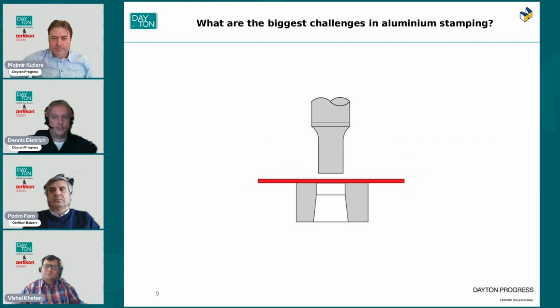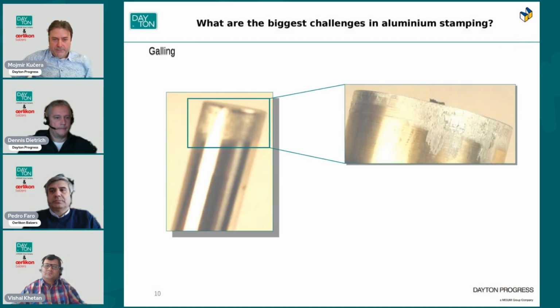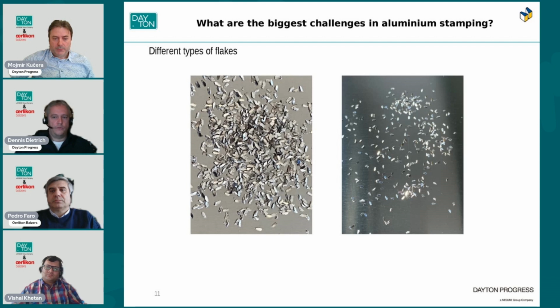Adhesive wear is caused by friction between the surfaces of the punch and the sheet metal blank. When punching non-ferrous materials such as aluminium, aluminium alloy, copper, or brass, material sticks on the punch. This leads to the formation of a build-up edge and later to flakes when the punch dives into the die. Here we now see two pictures of punches with galling. Punches with galling cause fractured or broken punches, stripping problems, poor quality holes, fast tool wear, or flake generation. In these two photos, we see flakes taken from a tool in which aluminium parts were made.